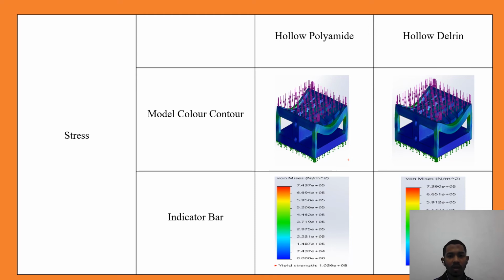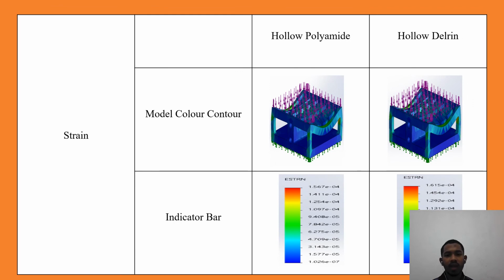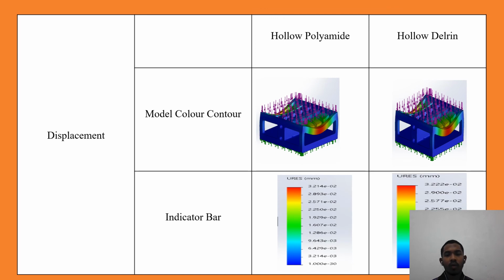This is a comparison result of a static analysis between a hollow polyamide vacuum block and a hollow Delrin vacuum block. You can see the indicator bar, which is the stress obtained from the hollow Delrin vacuum block is lower than the stress obtained from a hollow polyamide vacuum block. The strain is likely the same as the stress between a hollow polyamide and hollow Delrin. For the displacement, we can see the displacement is not too different.